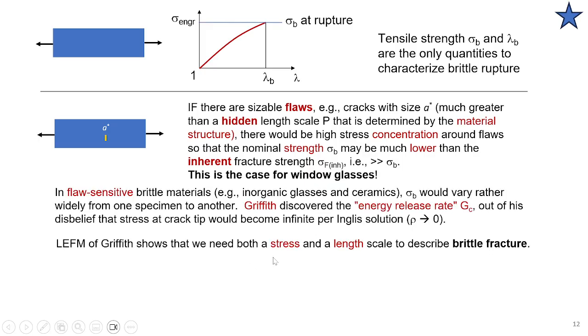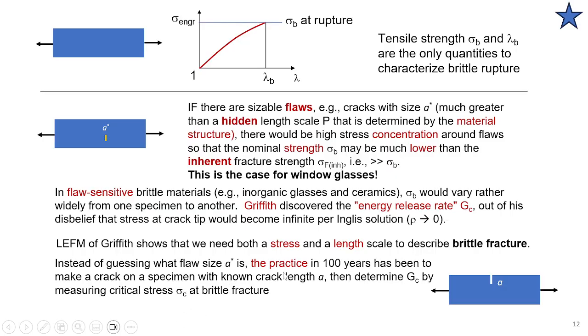And that's what Griffith did. So Griffith's discovery of the energy release rate precisely says there is a quantity that controls fracture that involves both the strength and the size of the crack. So 100 years of practice is we suspect there's a flaw. Well, if there's a flaw, and I don't know the size of it, why don't I just make one that I know the size of and learn what the flaw is doing? And then you feed back to the system.